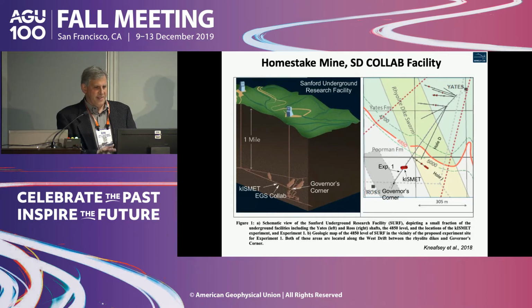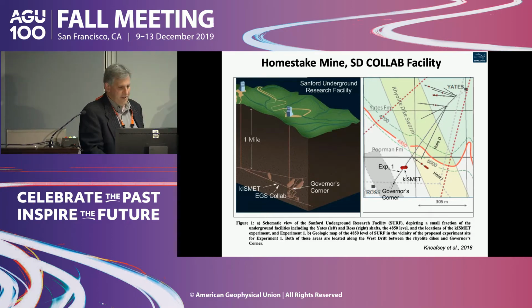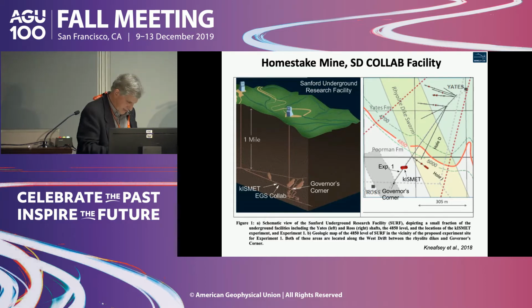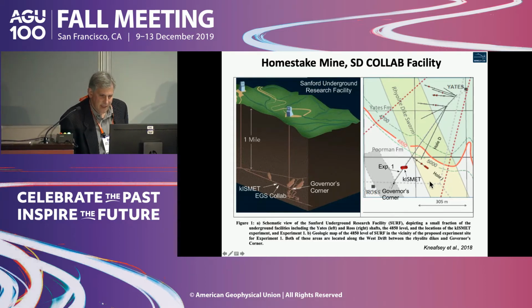What's the site? The Homestake Mine, the COLLAB facility in South Dakota. So we're at about 4,850 feet below the surface. The site is right here in this Poor Man Formation. There's also this dike swarm, and we're not far from the Yates Formation. Most of the mining is actually in the Homestake Formation, which is kind of off the sheet here, although there's a fair amount of sulfides also in the Poor Man.